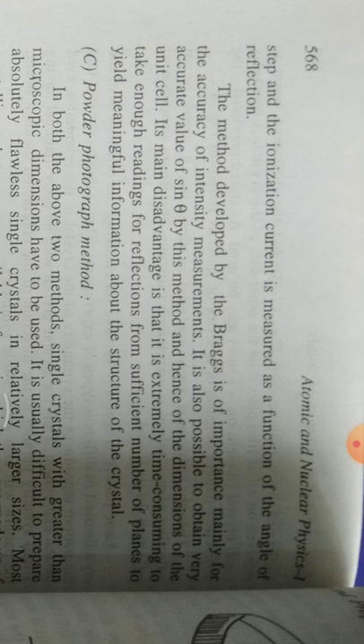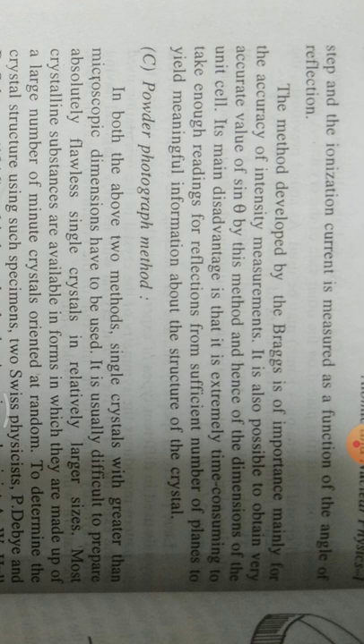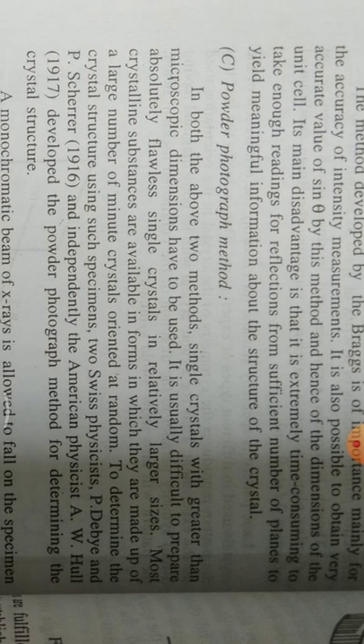The method developed by the Braggs is of importance mainly for the accuracy of intensity measurement. It is also possible to obtain very accurate values of sine theta by this method, and hence of the dimensions of the unit cell. Its main disadvantage is that it is extremely time consuming to take enough readings for reflections from a sufficient number of planes to yield meaningful information about the structure of the crystal.